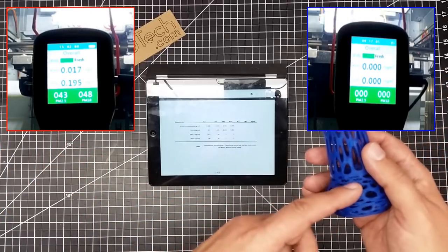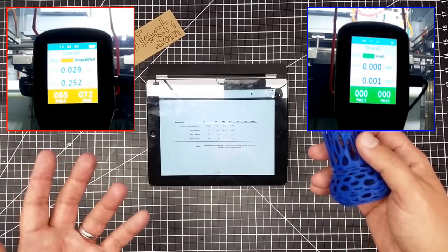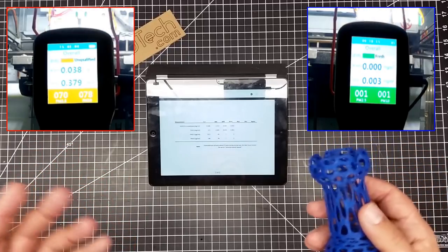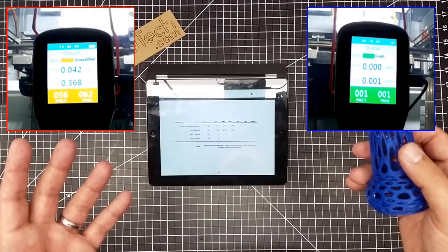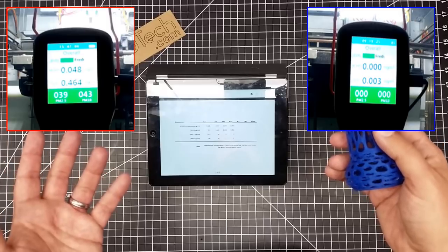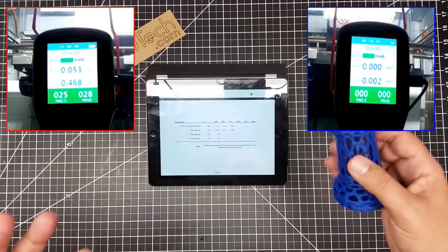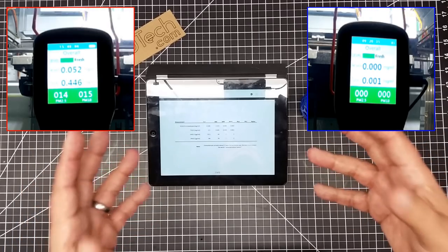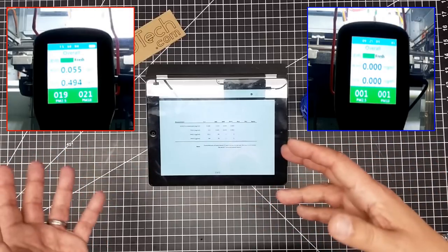Also, because of the addition of the glycol, I was thinking I would see something different than what I saw. I'm just going to jump into it. Literally, I saw basically no formaldehydes formed, very little VOCs formed, and very little particulate matter all in all formed by the release of this. Now, a little bit of a spoiler alert: I've come to find that things that like to stick to themselves emit fewer particles than things that don't stick to themselves very well.